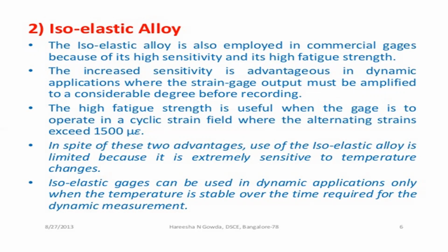So it has a very high fatigue strength and high sensitivity. The high sensitivity is advantageous in dynamic applications where the strain gauge output must be amplified to a considerable degree before recording. The high fatigue strength is useful when the gauge is to operate in a cyclic strain field where the alternating strains exceed 1500 microstrain.